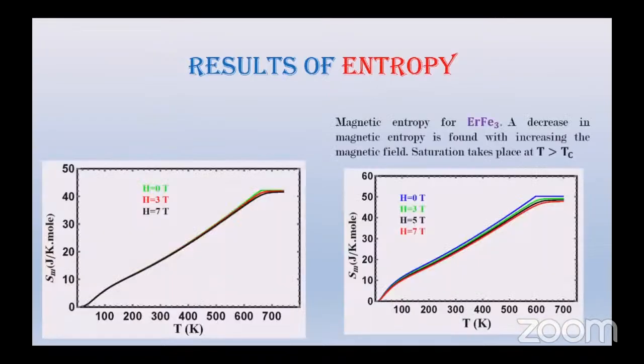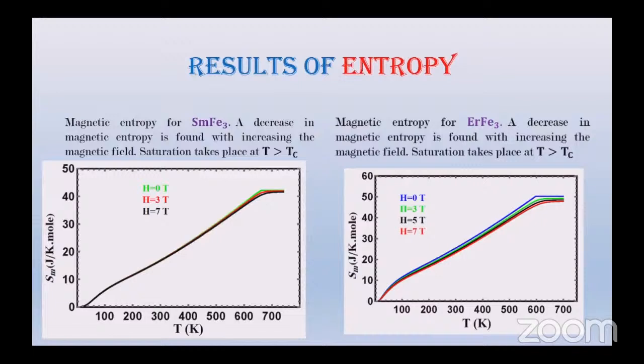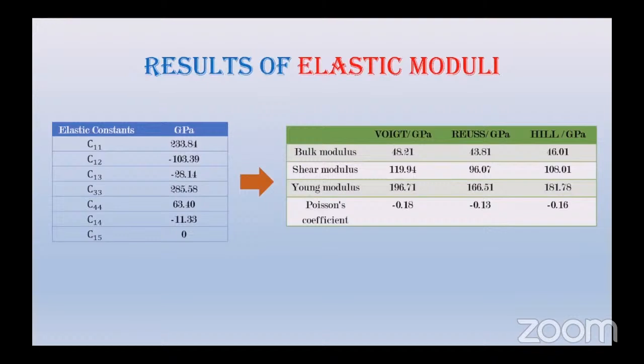Results of entropy. For the magnetic entropy of samarium iron 3, a decrease in magnetic entropy is found with increasing magnetic field, and saturation takes place at T greater than Tc. Results of elastic moduli. The calculated elastic moduli: shear, bulk, Young, and Poisson's coefficient for the rhombohedral samarium iron 3 compound.